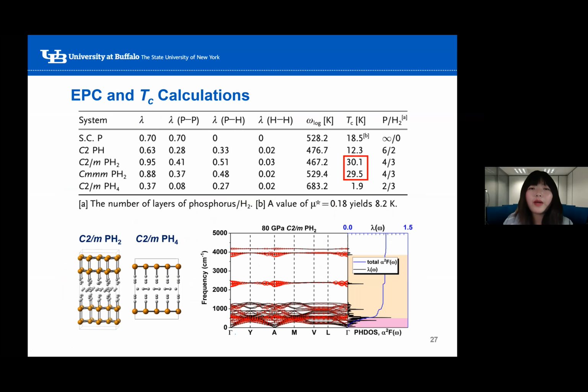So finally, we estimate the Tc values for the stable structures. The two PH2 structures give similar Tc values, and their electron-phonon coupling mainly originates from the phosphorus-phosphorus and phosphorus-hydrogen interactions. The hydrogen-hydrogen interaction region contributes a minor part. So this is very different from the high-pressure PH2 phase, which doesn't contain the molecular hydrogens.